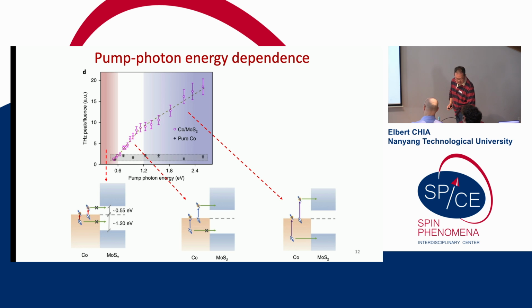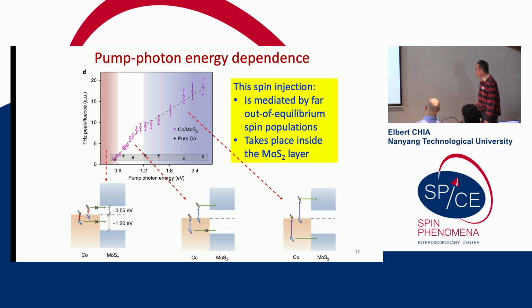And so this set of measurements show that this spin injection is mediated by the far out of equilibrium spin populations, and they take place inside the MoS2 layer. Why? If we add these two values, about 0.55 and 1.2, this is more or less the band gap of single layer MoS2.